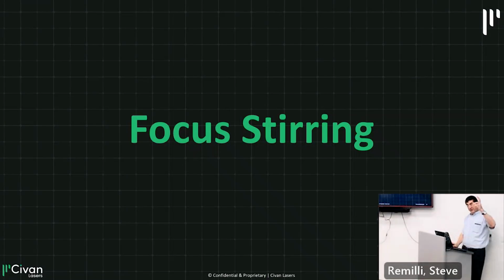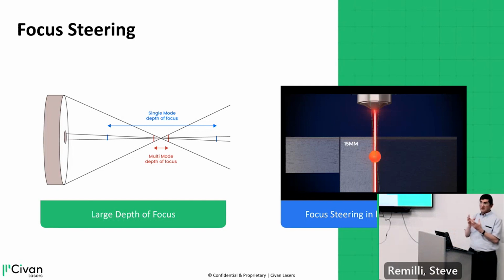And the last feature is the focus steering. Anybody who has worked with high power lasers knows that you have to work very, very close to the workpiece, and your depth of focus is very limited. Even if you work 20 centimeters away and you want to focus all this energy to 0.5 millimeter, you use a focusing lens. But the depth of focus is very small, meaning that if you are a few millimeters away from the focus, already the spot is very big. So you go out of focus very quickly.